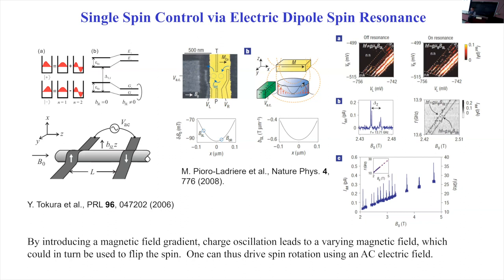It turns out that with a magnetic signal, it's a pretty difficult task to get fast enough rotation, because you basically need to pass a big AC current through or next to the sample, which would cause all sorts of issues if you pass a big enough current, right? Heating, photon-assisted tunneling, things like that. So people came up with the idea of driving this spin rotation using an electric field instead of a magnetic field. Electric field also is very local, right? So you can choose any particular quantum dot and drive the local gates to rotate the spin.